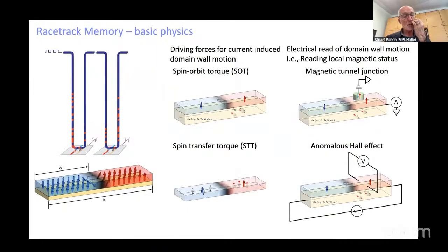And I want to just remind you of some basic physics. Originally, when I proposed this, we proposed moving the domain walls through something called spin transfer torque. Simply, current in a magnetic material is spin polarized, delivers spin angular momentum, and moves the domain walls. Subsequently, it was discovered by ourselves and others that there's another very interesting way of driving a domain wall, which is something called a spin orbit torque. In this case, the spin angular momentum currents, or spin currents, spin polarized currents, are derived in layers like platinum or tungsten.